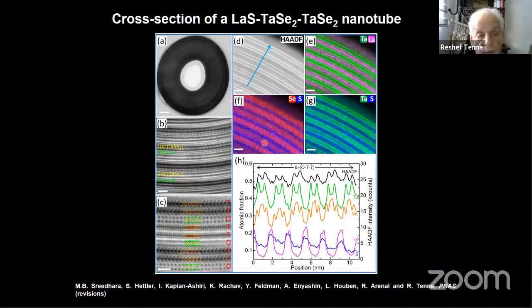I think this is the last slide that I want to show you. This is a cross-section of new nanotubes, which we have synthesized and is in PNAS in revision. This is a quaternary nanotube, but very interestingly, here we mix sulfur and selenium, and the sulfur combines with the lanthanum, but not with the tantalum. If you go to very small amounts of sulfur, basically the material is starved of sulfur. It forms multi-layers of tantalum diselenide because the selenium binds to tantalum only and the lanthanum binds to sulfur only.